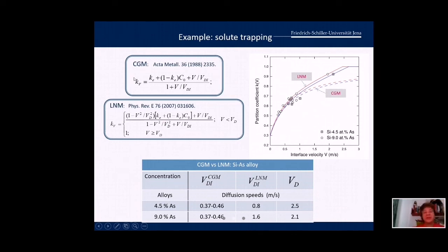liquid phase. However, if we have a very fast propagation of the interface with large driving forces, for instance, in additive manufacturing or in laser and beam treatments of the surfaces, in melt spinning or atomization, electromagnetic levitation, we have several hundreds of Kelvin of undercooling, or hundreds of thousands of Kelvin per second, and even several millions of Kelvin per second of cooling rates.